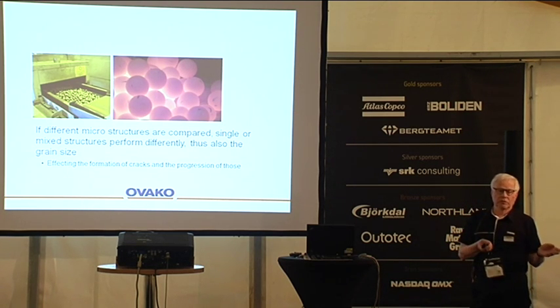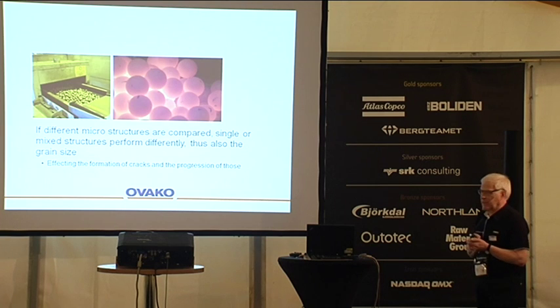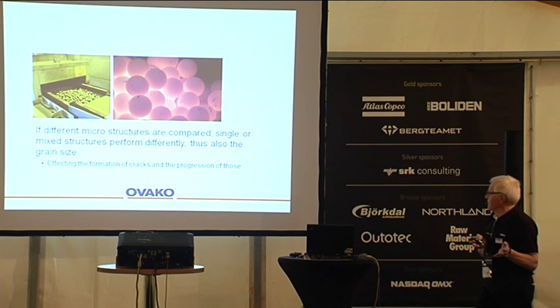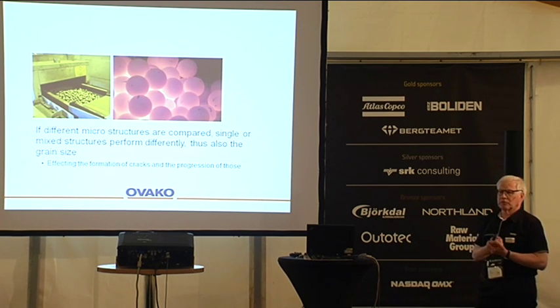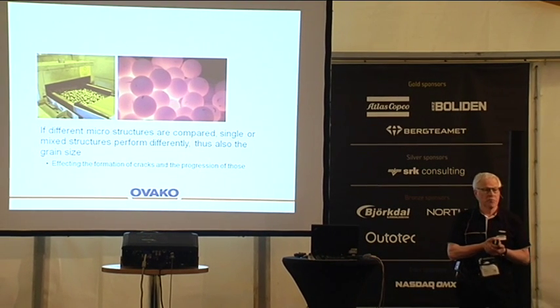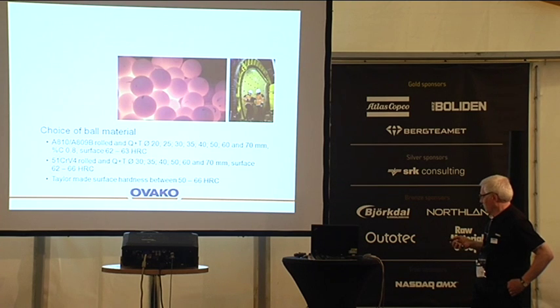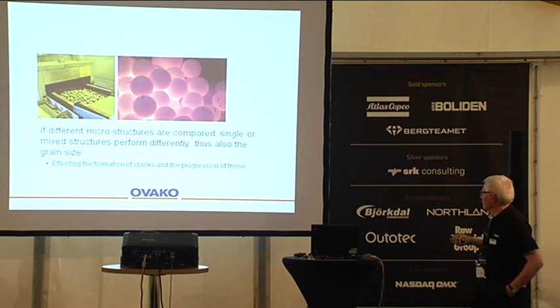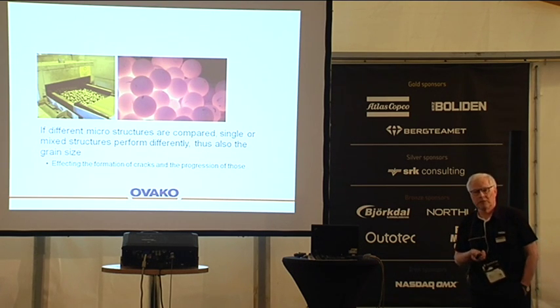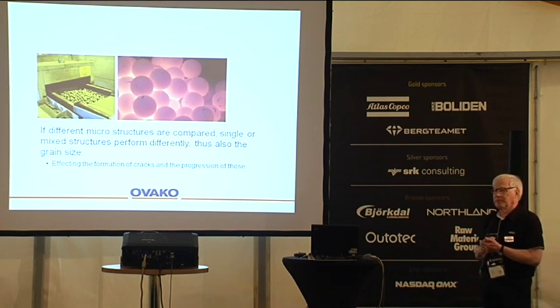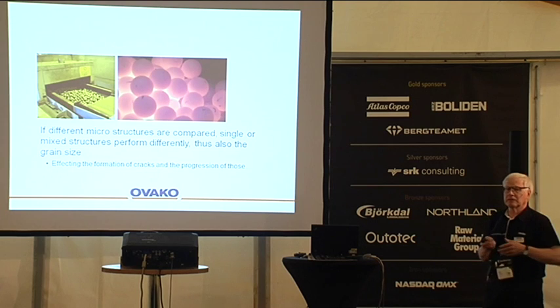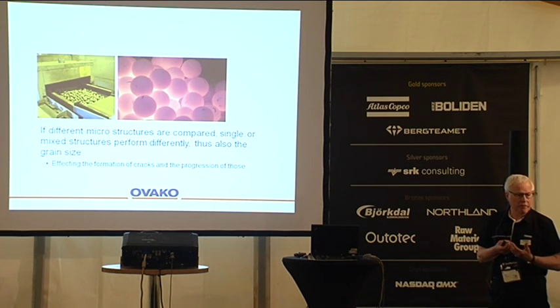Normally we try to have the same kind of structure in the grinding media, as we can see that it performs differently if we have a mixed structure. The grain size in the grinding media is also very important, especially when it comes to how the wear is progressing, to avoid formation and progression of cracks in the grinding media. That means that sometimes a grinding media with a lower hardness can have better performance than one with a higher hardness if you can control the conditions.